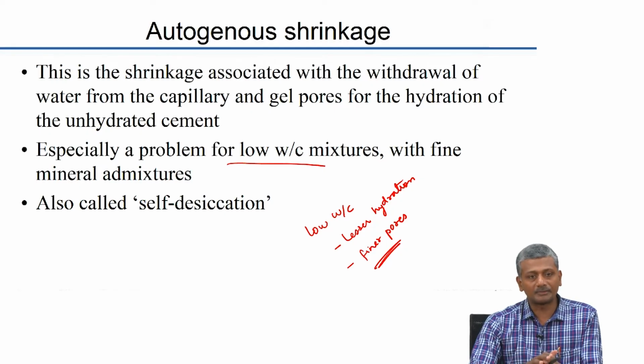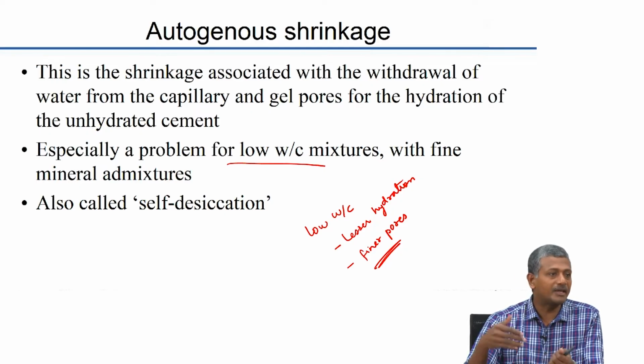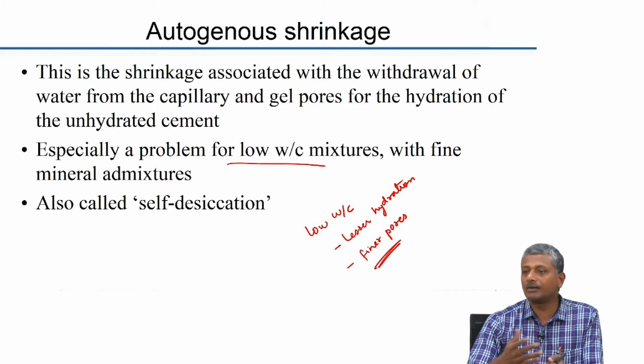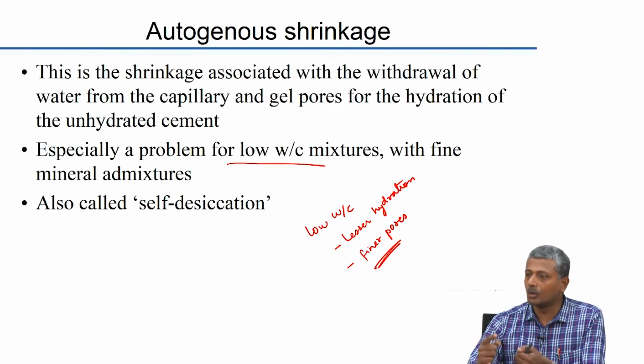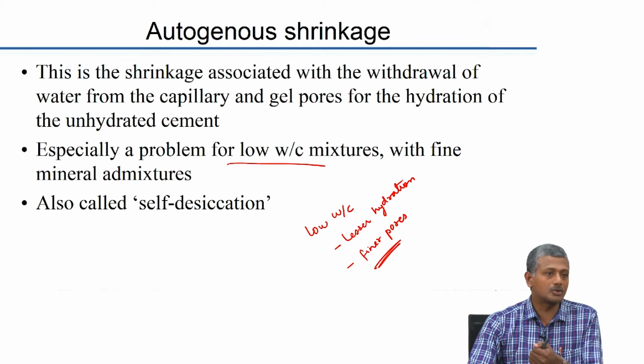When you do water curing, there is external water also that possibly can enter the concrete and reduce the autogenous shrinkage by a significant level. So, if you do long term water curing for concrete that is having low water to cement ratio, that can actually significantly reduce your autogenous shrinkage characteristics.